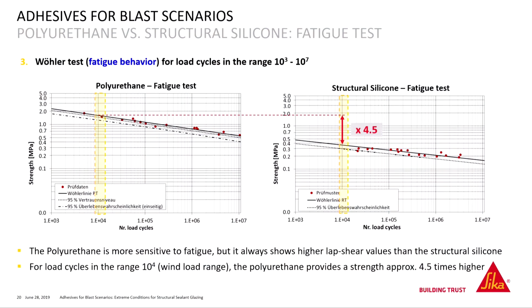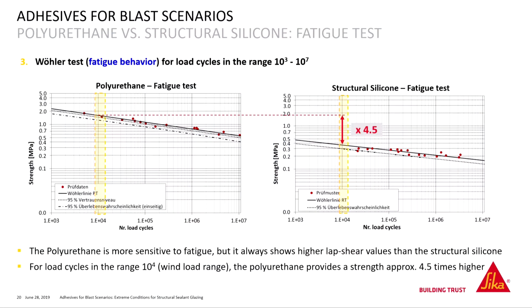Then let's come to the fatigue behavior. Polyurethane is said to not be the best performer under fatigue, under cyclic load, but that really depends where you start from. After 10,000 cycles, in this yellow range, polyurethane is even still 4.5 times higher than the silicone here.